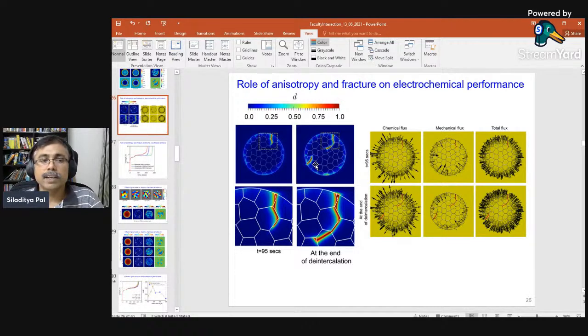Yeah, see, this is all de-intercalation. I don't want to confuse the charge and discharge cycle. So here it is de-intercalation. The lithium was already sitting within the material, so when we de-intercalate, a tensile stress field is generated. It is like when wood dries up and a crack develops in the wood. This is due to the de-intercalation of the moisture. A similar thing happens in this particulate composite type cathode. When the lithium is going out, we are considering that the extraction of lithium from the body is creating the strain.